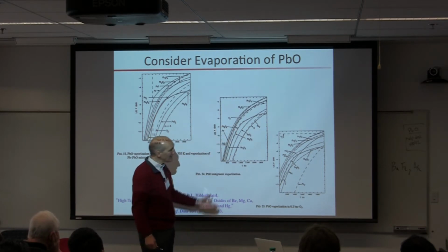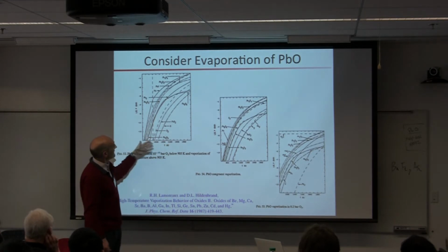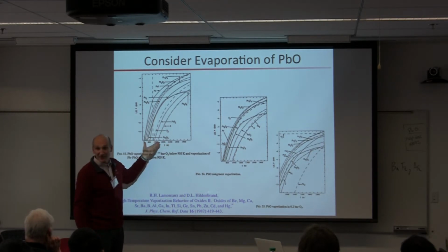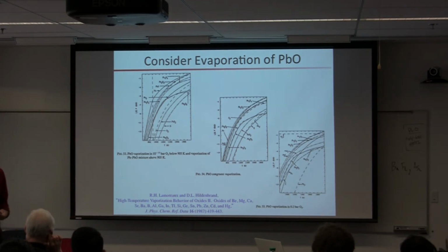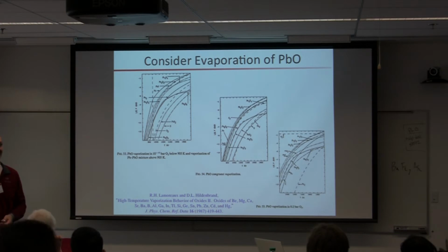And let me point out another problem of this. If you heat this up in hard vacuum, the composition of your source is changing over time. So what you get depends upon, well, was it fresh lead oxide, or not. That's not what you want in a process. You want to be able to heat up your source and get the same stuff off all the time. That's why in general we use elemental sources. You heat up an element, you get just that element coming off. Some elements are a little more tricky. They might be clusters. You heat up arsenic, you get mainly As4 clusters coming off. If you heat up bismuth, you get mainly Bi2 clusters coming off. But you're getting just the element coming off, and it's not changing your source over time. Now there are some exceptions to this.